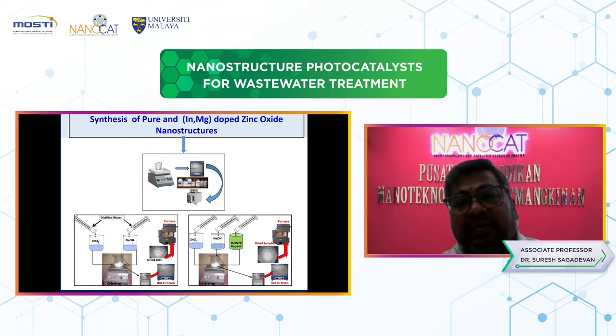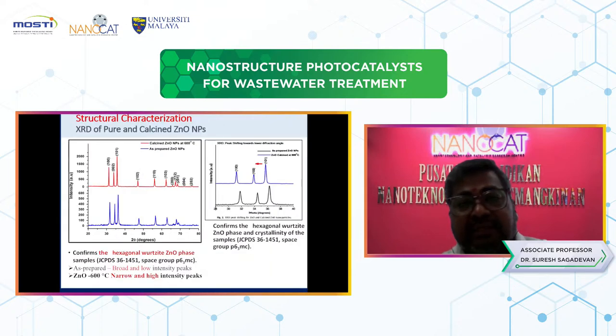How it became like this for photocatalytic activity and degradation, we checked using the two dopants with the zinc oxide. If you look here at the structural characterization by XRD of pure and calcined zinc oxide nanoparticles, you see the XRD pattern of the as-prepared sample without any calcination. You look at here that the intensity is very low and the peaks are very broad. But with calcination at 600 degrees Celsius, the peaks are narrow and high intensity. This material, zinc oxide, confirms the hexagonal wurtzite phase, which matches the standard JCPDS code number.